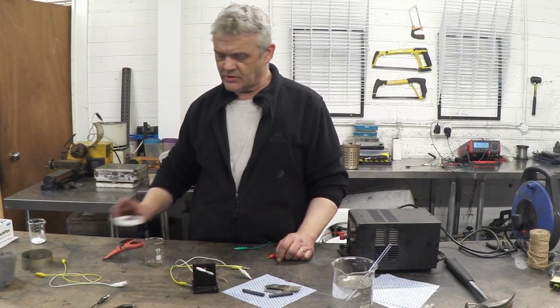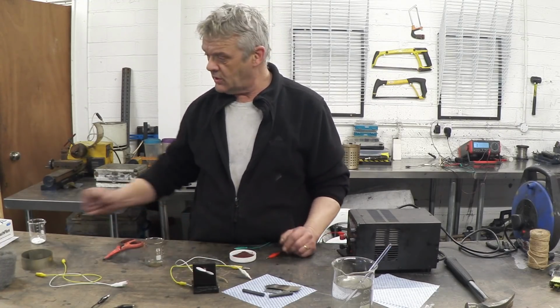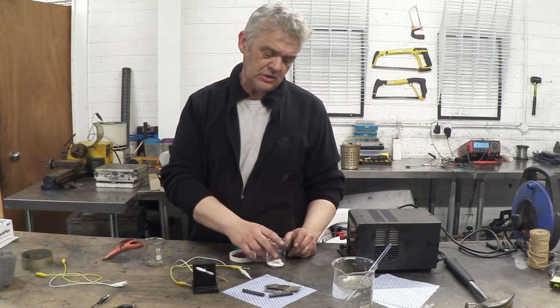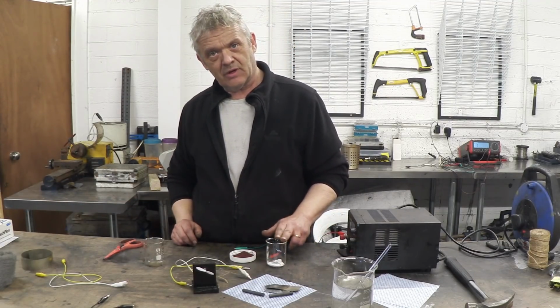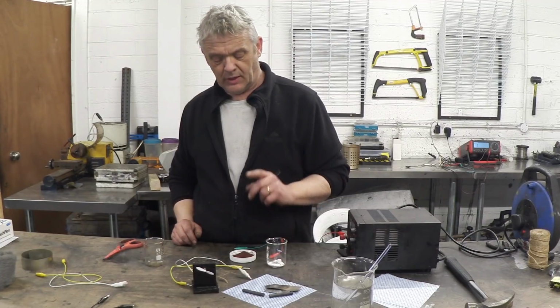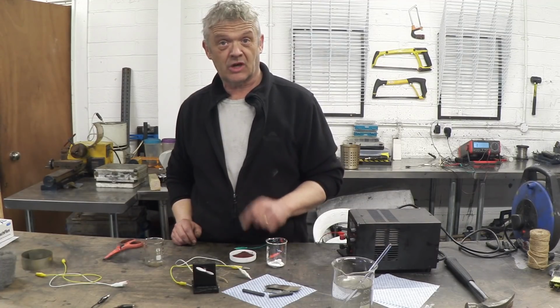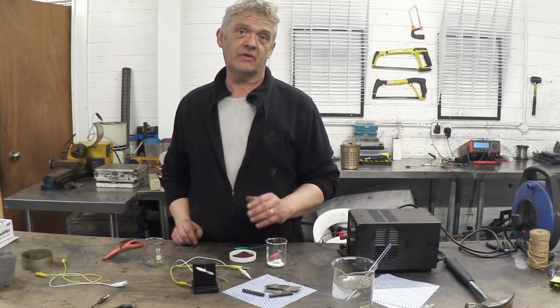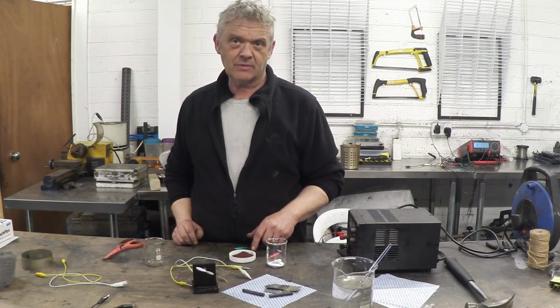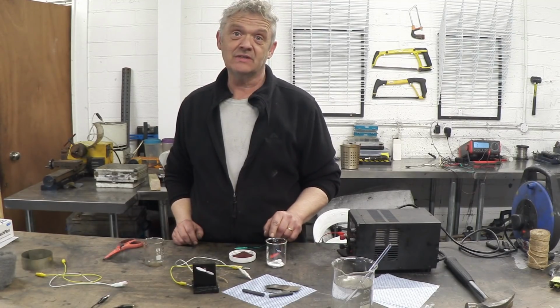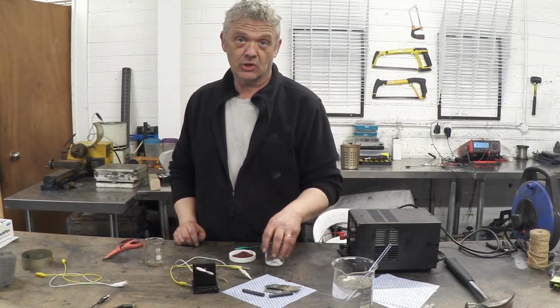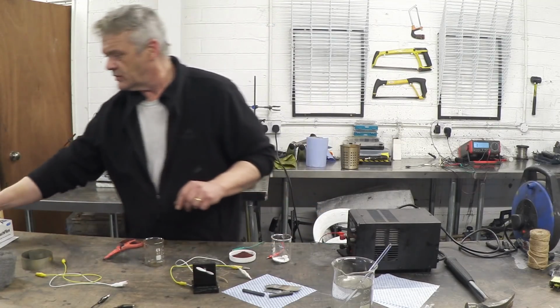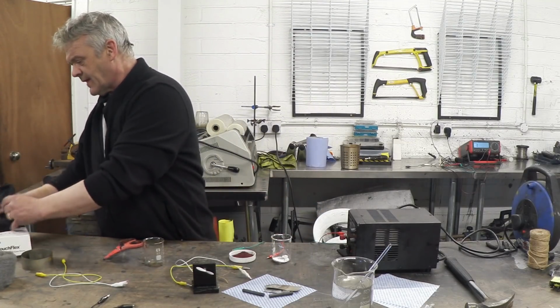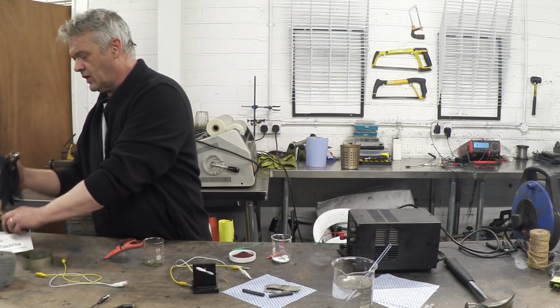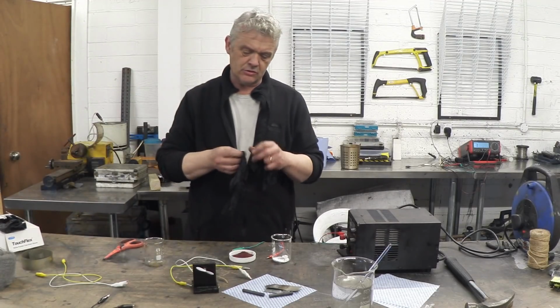This depolarizer was black copper oxide, which I've got here, and you make the paste using magnesium oxide, magnesium chloride, and black copper oxide, and you mix those in a ratio of 25 to 1 to 1. There's 25 grams of copper oxide there, 1 gram of magnesium oxide and 1 gram of magnesium chloride, and you mix that into a stiff paste. Then that stiff paste is spread onto an iron sheet and allowed to dry.